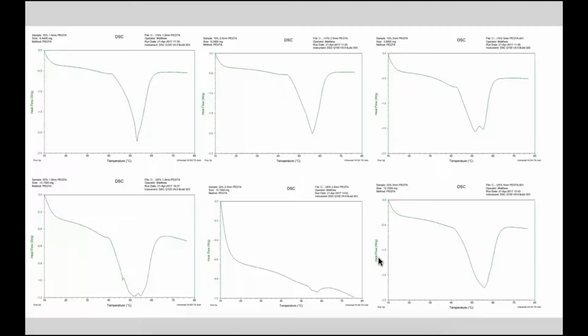Furthermore, the lowest crystallization temperature from our samples was around 51 degrees Celsius with a 20% PEG at 1.5 minute exposure. The crystallization temperature is relevant to our project because we don't want the hydrogels to soften inside the body in case a person has a fever. The peaks start forming at around 42 degrees Celsius, which is still above a deadly fever temperature.